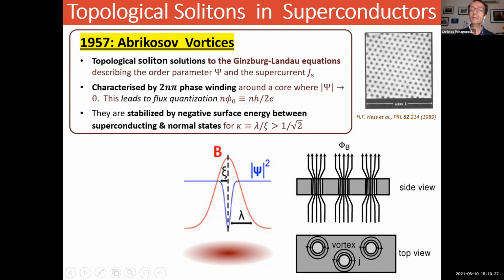So here is a nice typical image of the vortices from the top, and this is a side view of the sample as the magnetic field goes through the superconductor. And the critical parameters are essentially the order parameter, which goes to 0 at the center of the core, the magnetic penetration depth, which is the region over which the field penetrates, and the coherence length, which is approximately half of the size of this vortex.